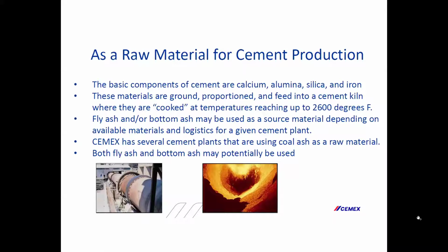We also, in some cases, use fly ash as a raw material because to produce cement, you need materials that contain calcium, alumina, silica, and iron. And fly ash could potentially be a good source for some of that. Whatever the source of materials we're using, we grind these up, we proportion them, and we feed them into the cement kiln at temperatures up to 2,600 degrees, and we basically cook it. And what comes out of the kiln is called clinker. We take that, and it goes to a finish mill along with some gypsum to control the set, and we grind it, we come up with cement.